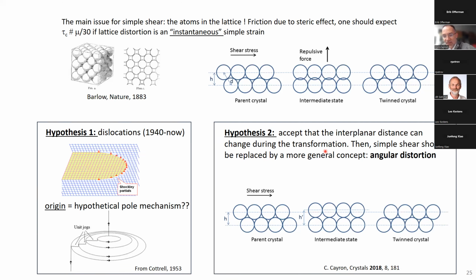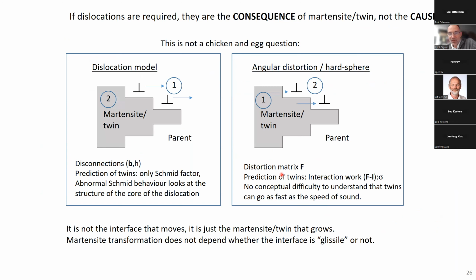So there is a second hypothesis that I try to introduce, which is to say there is no obligation for the atoms to respect a simple shear. I mean, why not imagine that the interatomic distance can change in the intermediate state to go from here to here? Why not leave the atoms rolling on each other? And it's even more the case if you take into account that during a martensitic phase transformation, there are some softening modes in which chemical bonding can decrease. But if you continue with this point of view, you say that it is the martensite that creates the dislocations and not the dislocations that create the martensite.